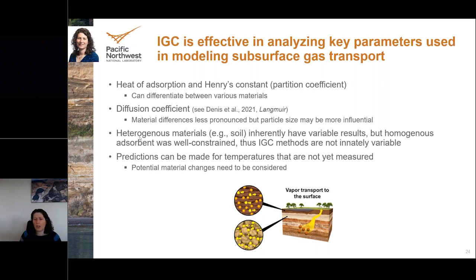And then the heterogeneous materials like the soil inherently have more variable results, but by comparing our results to the homogeneous sorbent, I didn't go into detail for this talk, but the homogeneous sorbent measurements were well constrained. And so this really highlighted to us that the inverse GC methods are not innately variable. It's really the material that is causing that variability in the results.